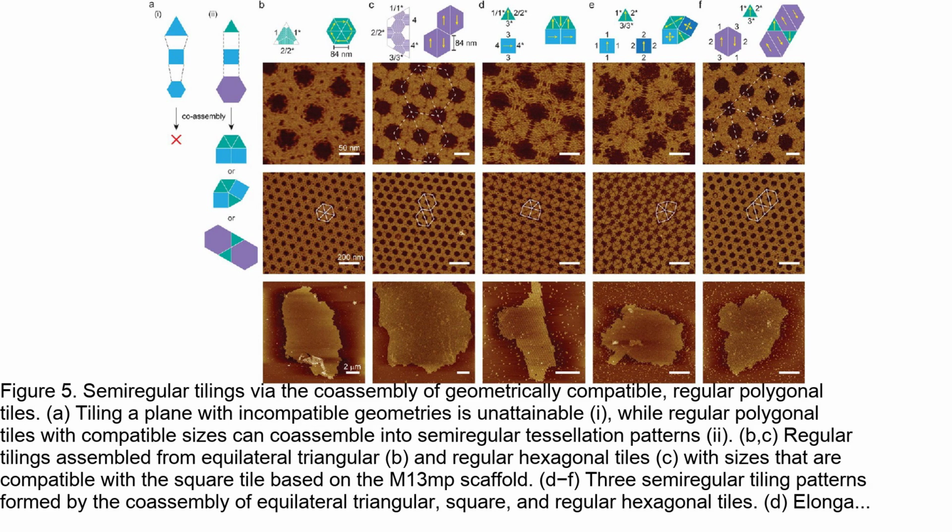Figure 5 in the paper shows several examples of tessellation patterns assembled from DNA origami tiles. The authors used a general method to create DNA origami tiles that grow into tessellation patterns with micrometer scale order and nanometer scale precision. By finely tuning the interhelical distance, d, they were able to accurately design the monomer tiles and improve the tessellation capability.